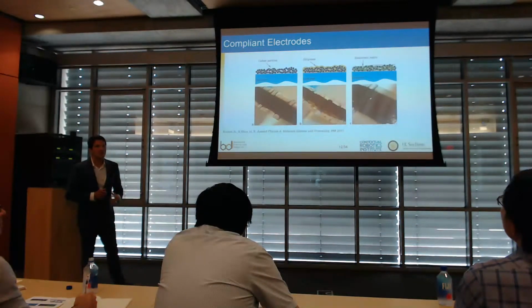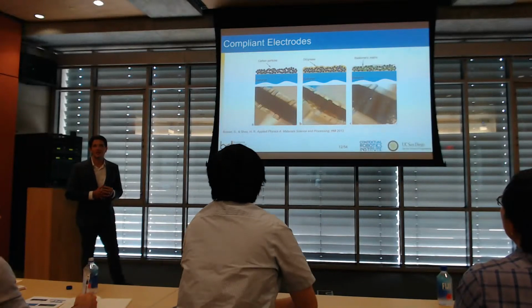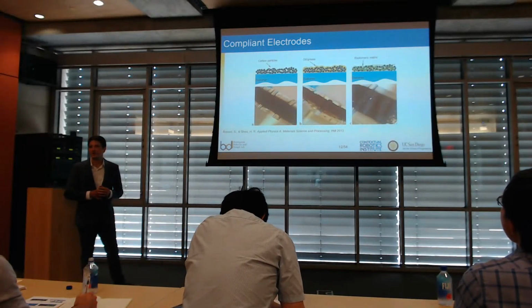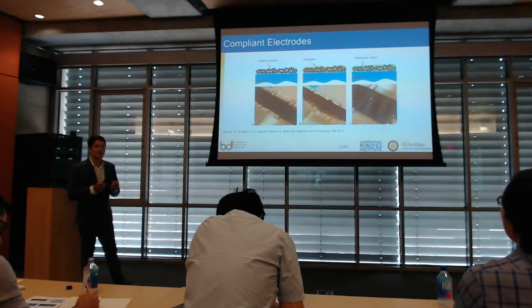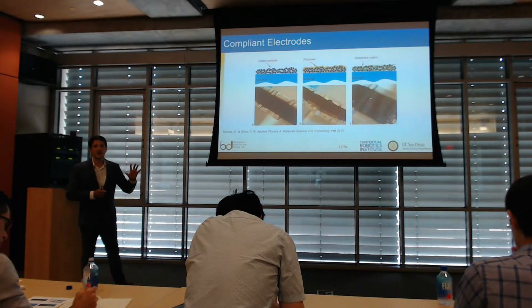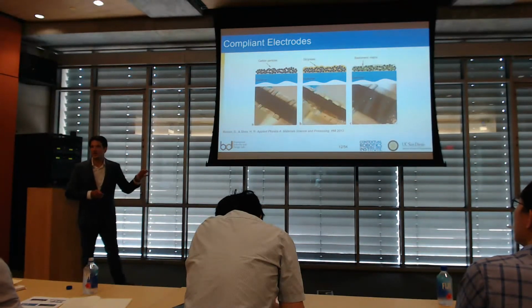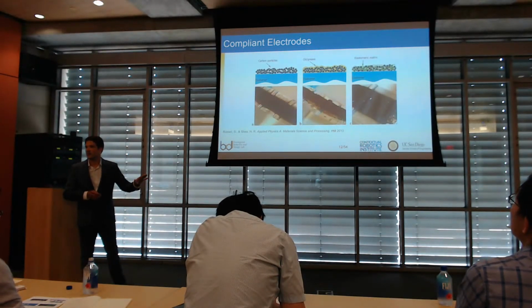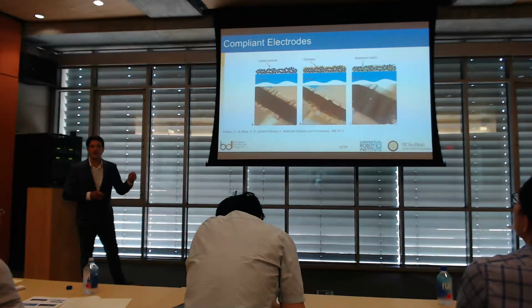Okay, so that was the material for the elastomer. The other material that we need to consider is for the electrode. So you want a compliant electrode, so something that can apply electricity but won't change the material properties of the actuator. And so what many groups use are carbon-based electrodes. So the one on the left is carbon particles. So if you have graphene or carbon nanotubes, you can just apply them directly to your actuator, and that will conduct the electricity. Or you could use carbon grease, so it's carbon particles suspended in a grease.